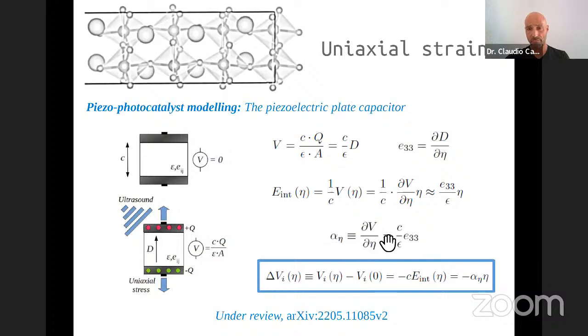So based on this simple equation, we can consider that the maximum band bending over a unit cell for a given material like this would be equal to this alpha eta parameter defined here, equal to the piezoelectric coefficient E33 divided by the electric constant, multiplied by the strain that we applied, again considering a linear approximation. So in terms of band alignment tunability as induced by strain, good piezo-photocatalytic materials should exhibit large alpha eta parameters. Because then we will have large band bendings, we will have large internal electric fields created in the interior, and therefore we will be able to, just by applying very small strains, sorry, not epitaxial, just strains,